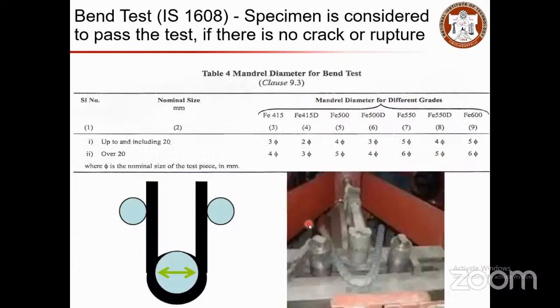So how do you do the bend test? So IS 1608 gives you the specifications to do the bend test. So when you do a bend test, the specimen is considered to pass the test if there is no crack or rupture. So you have a mandrel diameter like this. So you keep your rebar going through that, and then you bend it to 135 degrees. The mandrel diameter should not be too large. So you have to keep a relationship between your rebar diameter and then the mandrel diameter, which will be bent to induce the stress on the surface.